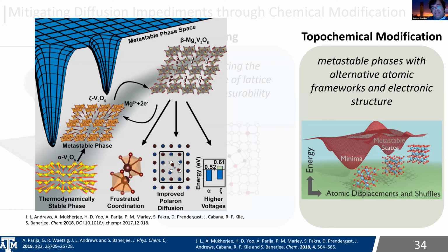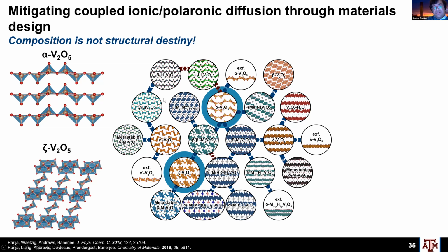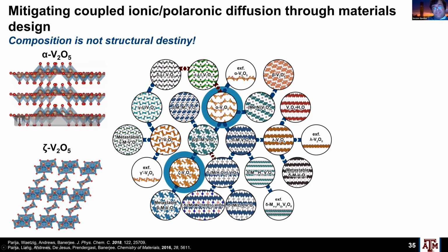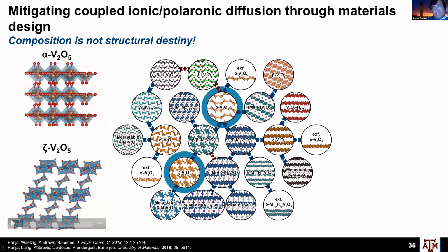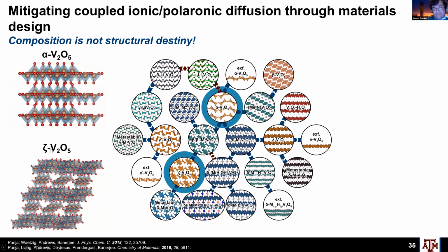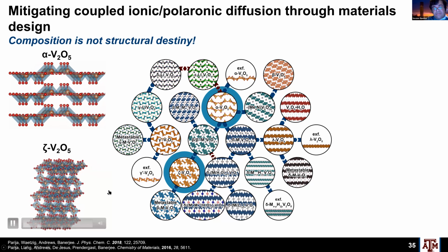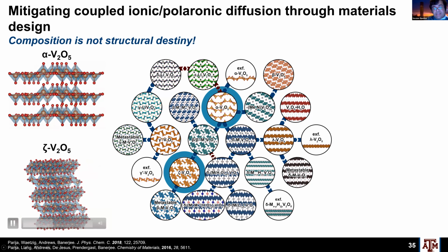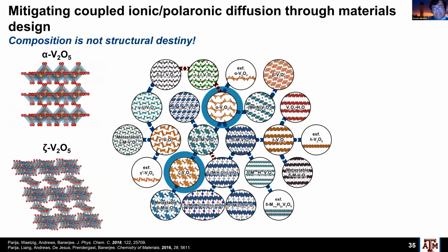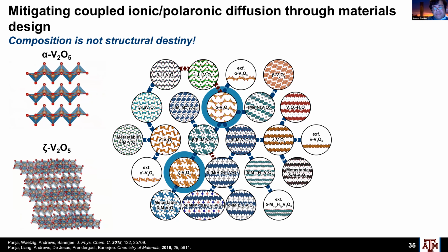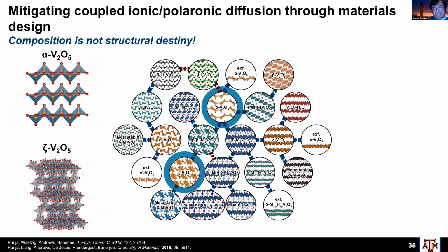And actually, V2O5 turns out to have a very rugged landscape. And these metastable phases, when you stabilize them, oftentimes have very intriguing diffusion pathways that allow us not just to do lithium ion insertion, but also magnesium and calcium ion insertion. Okay, and in the interest of time, this is alpha V2O5. I'm going to show you just a few examples of structures that we have that are well characterized. This is one we particularly love, zeta V2O5. It's got these 1D tunnels that are defined, and these 1D tunnels tend to be really great for inserting lithium ions as well as magnesium ions.